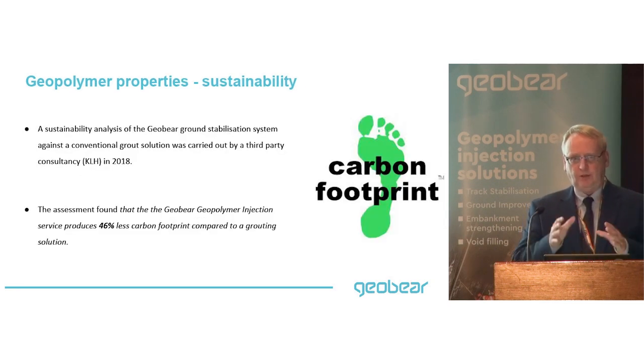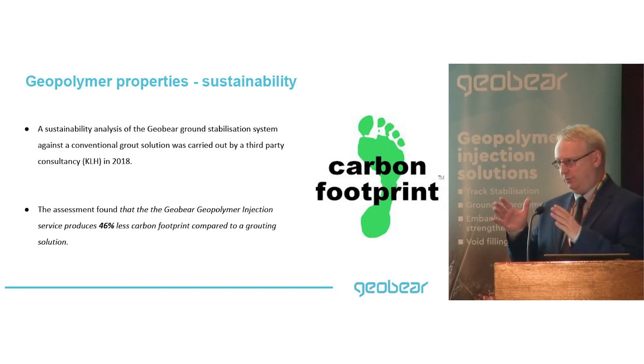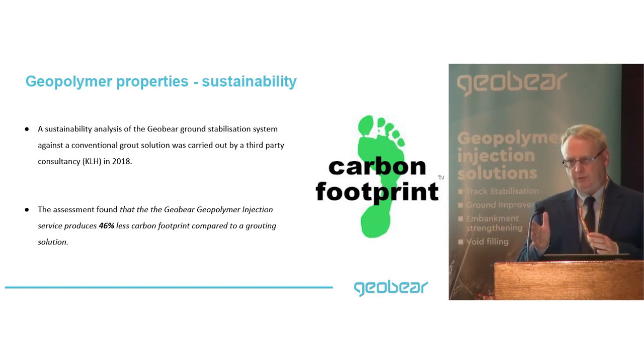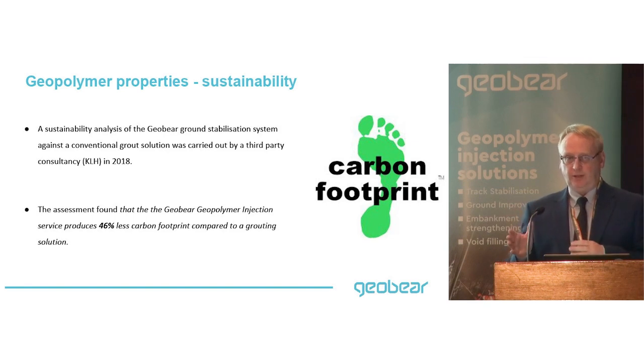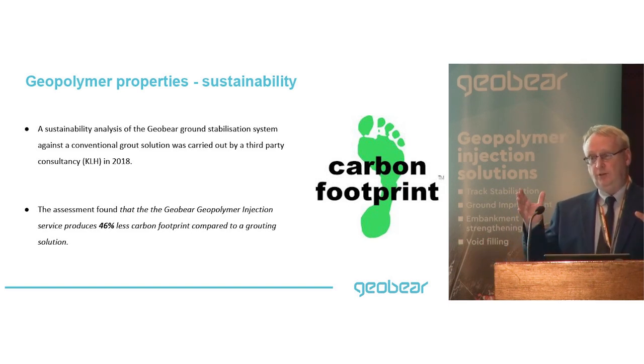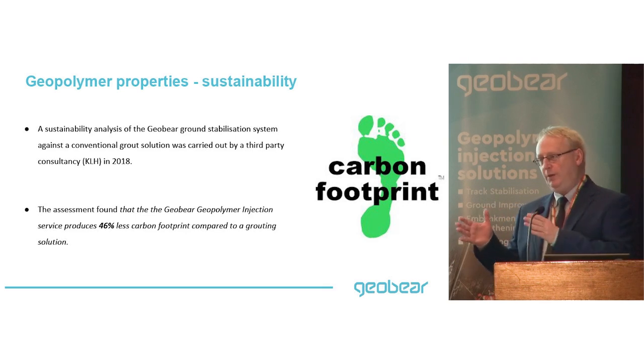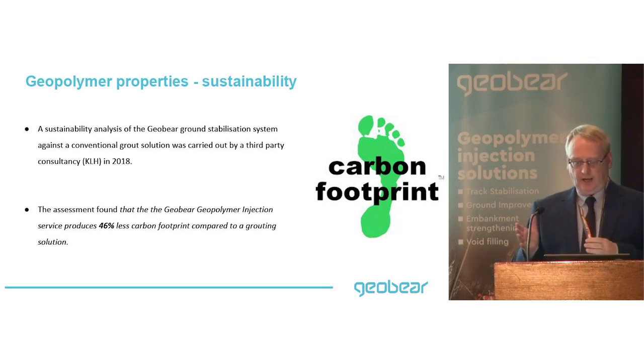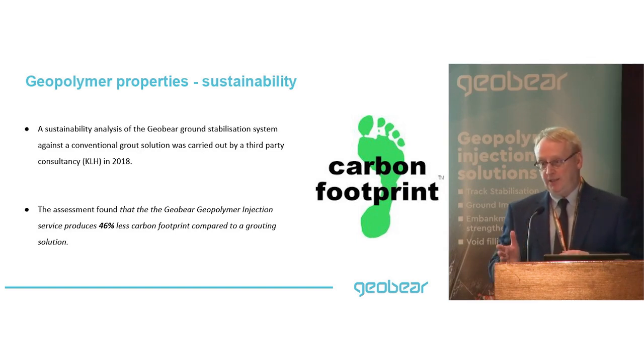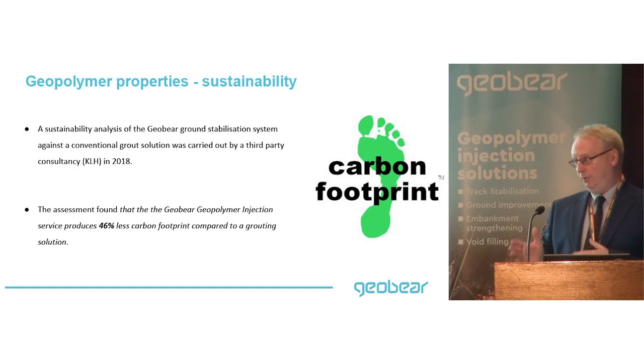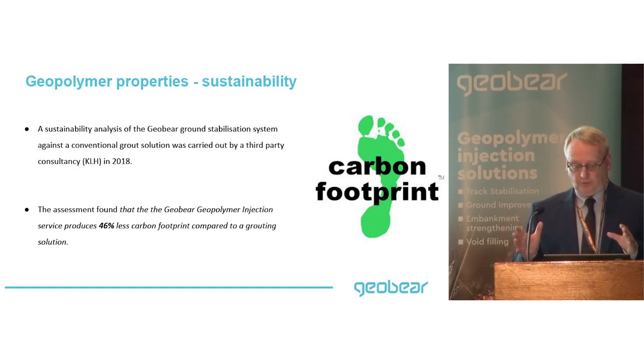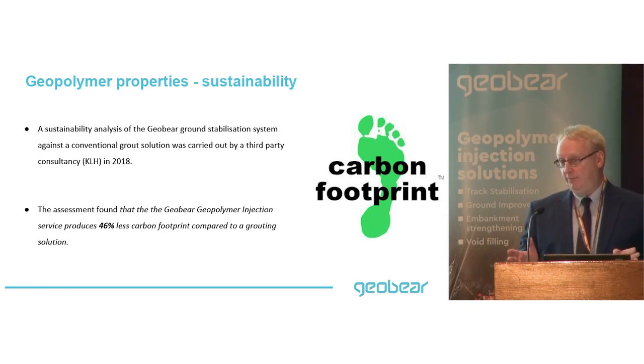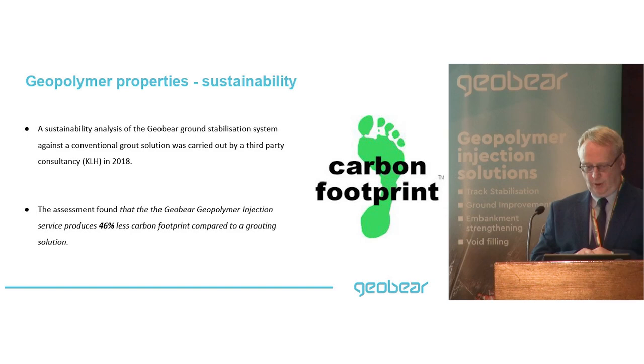The other thing to consider is carbon footprint. Compared to traditional cement-based grouts, we use a lot less material to achieve the same end result, which generally means the carbon footprint of geopolymer-based solutions is lower than conventional solutions. We've had this independently verified by Carbon Footprint Limited, who've done carbon study analysis on our projects comparing our approach against conventional treatment. We're looking at roughly 46% less carbon emitted on typical rail-based infrastructure projects. It varies by project type, but for rail-based solutions it's roughly half the carbon emitted, which is a good positive thing for geopolymers, in my opinion.